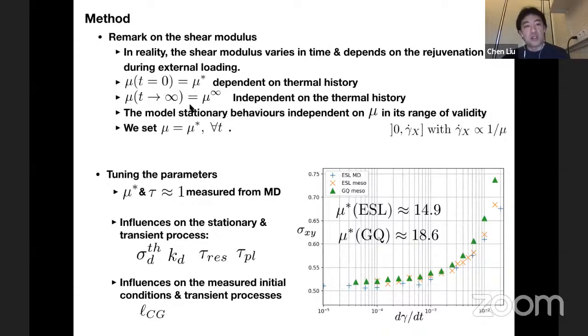So there's a missing part of the dynamics of the shear modulus, but the model has an advantage: the stationary behavior of the model within the range of validity is independent of the shear modulus. And the range of validity in terms of shear rate is from 0 to a crossover shear rate, where the crossover shear rate is inversely dependent on the shear modulus. So for simplicity, we set once and for all the shear modulus equal to its initial value, and then also for producing the correct transient behavior.